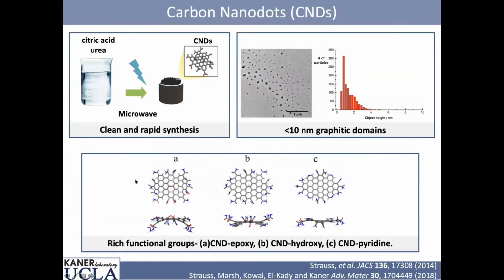Okay, so how do we address this problem? We're working on something called carbon nanodots. You can take organics like citric acid and urea, microwave them, and you get these little dots that are pretty close to pure carbon. Here are the dots. They center around 1 nanometer, with a little bit of size difference. They have different functional groups depending on what you used, so they might have some nitrogen, some oxygen, and so on.